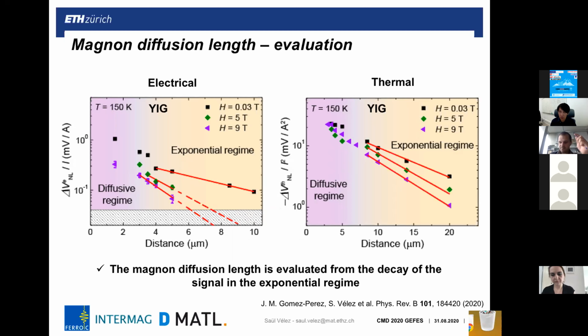I mean, you should make resonance experiments to just prove one wavelength. But the idea is that you cannot avoid generating different distributions. And the question is that only the low frequency magnons are the ones that propagate to much longer distances. And what you measure is the average of all the distribution. So you don't measure only a single magnon with a very narrow frequency range. You excite a distribution, and what you measure is the average of this distribution. That's what you detect in the experiment.